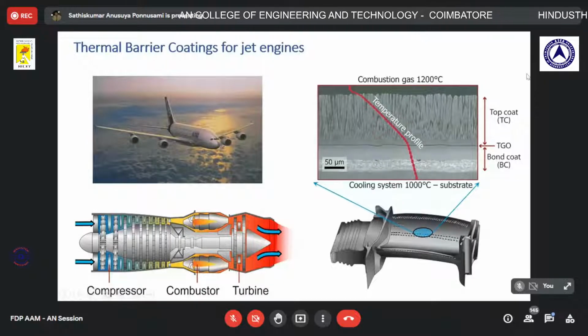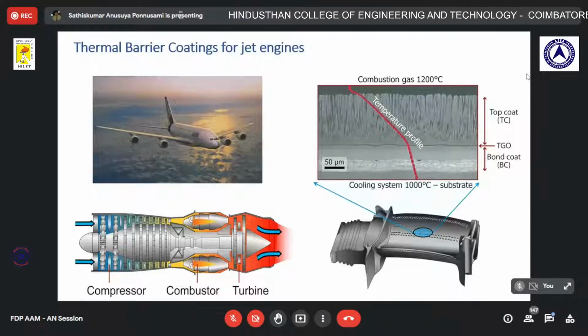Okay, and why am I showing this picture is that this particular microstructure shows you a coating layer which is made of both metallic and ceramic constituents. Yeah, so imagine you have a metal and then a rubber layer bonded together, and you put it in the oven, you heat it up. What happens? Because the two materials that are bonded together have different, let's say, characteristics, one expanding more than the other, naturally what happens? You develop thermal stresses, isn't it? Because both of them are bonded together, but one of them tries to expand more than the other. So you naturally develop the so-called thermal stresses.